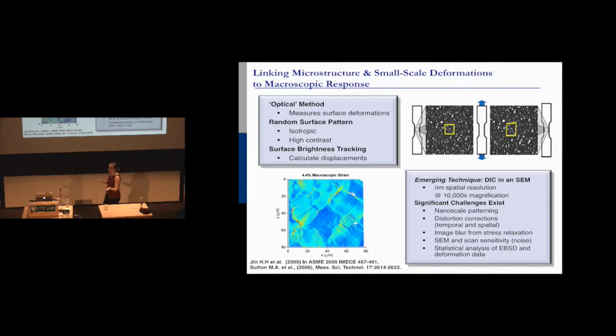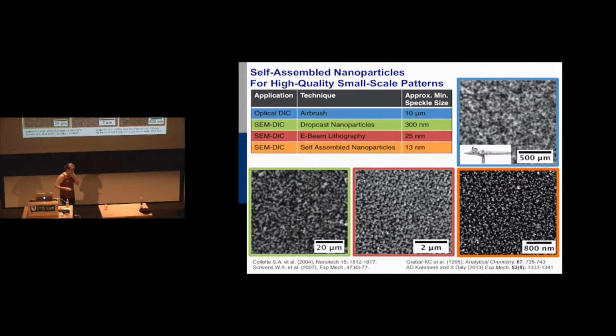We ended up doing this from about 10 micron field of view up to about 300 micron field of view. So when we first started, we had a bunch of stuff we tried. We tried depositing chemical vapor and lifting it off. We tried blowing gold through TEM grids. We tried all sorts of stuff. One of the first things we tried was actually E-beam lithography, which is the deposition technique. And the problem with that, this is right here.